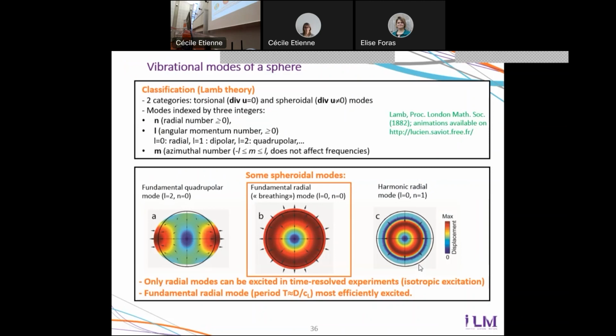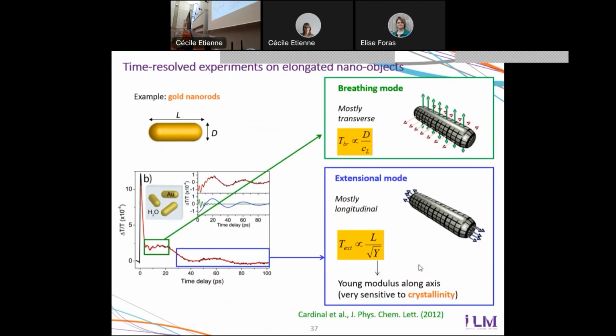And the vibrational periods that were measured are in very good agreement with those computed using Lamb theory for this mode. Just to mention, if the objects are more complicated, for instance an elongated object, it's not only a single mode that is detected. For gold nanorods, we have two modes with very different features which are detected. One with a small period associated to transverse vibrations, with a period proportional to the diameter, and one with a much longer period proportional to the length, which corresponds to longitudinal vibrations.